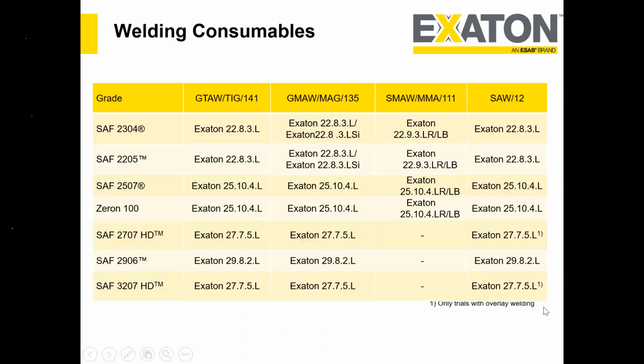So okay, these are basically the recommended grades on Exaton. For the lean duplex and duplex, we are recommending the duplex grade for TIG. For GMAW it is also duplex, specifically with the addition of silicon. Silicon gives us good fluidity in the liquid weld metal, and if you do the MIG welding with greater control of the fluidity, it really gives a very nice weld bead.